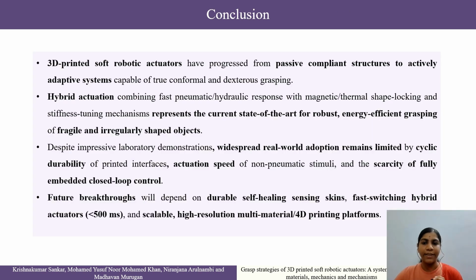In summary, 3D printed soft actuators have evolved from being just passive, compliant structures to actively adaptable systems that are capable of true conformal grasping. The current state of the art combines fast pneumatic or hydraulic actuation along with magnetic or thermal shape locking and stiffness tuning, which enable robust handling of fragile and irregularly shaped objects. However, certain challenges do remain. Cyclic durability at printed interfaces, slow actuation speeds for non-pneumatic stimuli, and the need for fully embedded closed-loop control systems still remain.